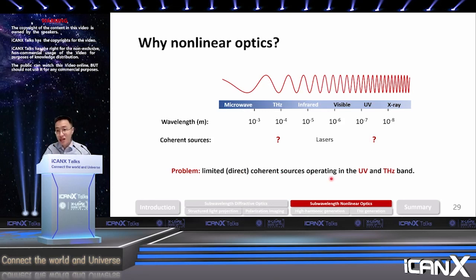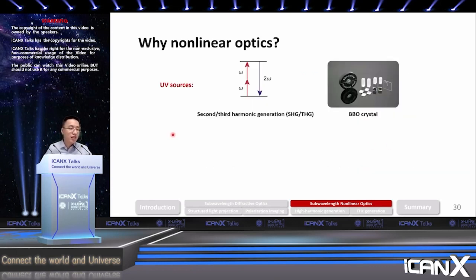In last week's iCANX talk, Professor Jagdish mentioned that you can use ultrafast dynamics in semiconductor nanowires, using the photoconductive effect, to create a broadband terahertz source. There is another way to create UV and terahertz sources, through the principle of nonlinear optics. For example, with a Ti:sapphire laser at 800 nanometers, using second or third harmonic generation, you can upconvert the photon energy and get UV light, using a nonlinear crystal such as BBO.